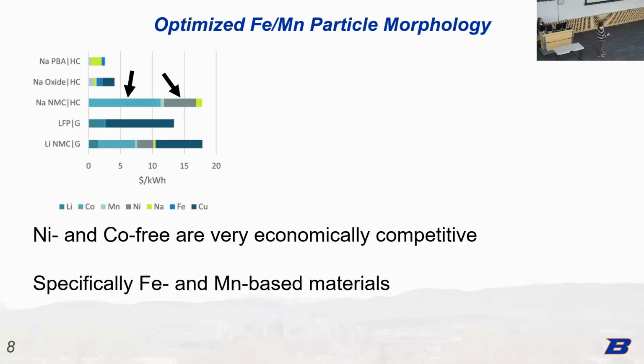Now, I kind of mentioned this earlier. When it comes to what is making economical sense for these materials, you want to exclude nickel and cobalt and instead focus on nickel and iron. No, you want to exclude nickel. You want to use iron and manganese because, as you can see, this is the cost per kilowatt hour. If you exclude the nickel and the cobalt, you actually reduce the price of these materials by about 300% or so. So I guess, can you reduce anything by over 100%? You can't, I'm sorry. You can reduce it by a factor of 3.